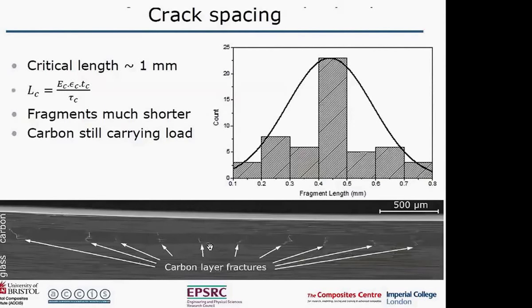We measured that. If you do a typical calculation you might do for tension, using a decay type equation to work out what the length is to get the load into the fibre, then you find that the critical ply length is about 1 millimetre. But actually, the distribution of these fragments is much smaller. It's about 0.5 millimetre on average, but some can go right down to 0.2 millimetre or less. So these fragments are very close together, much closer together than that critical length.